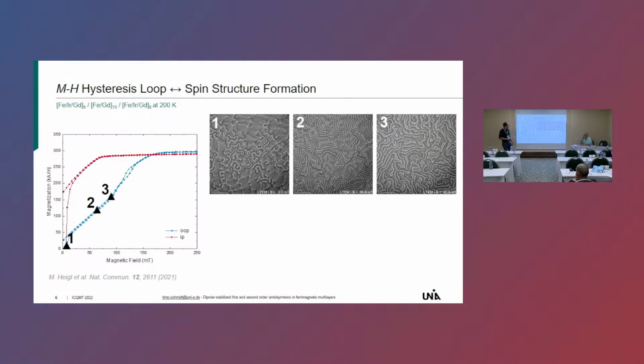If we increase it further, we can see that the trend continues. Basically, we have some Skyrmions. Then we increase it further, and now all of the stripe domains have been broken apart into a lot of bubbles, a lot of Skyrmions, and also some anti-Skyrmions here, here, and here.